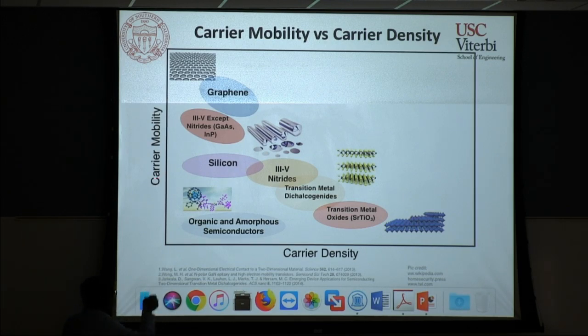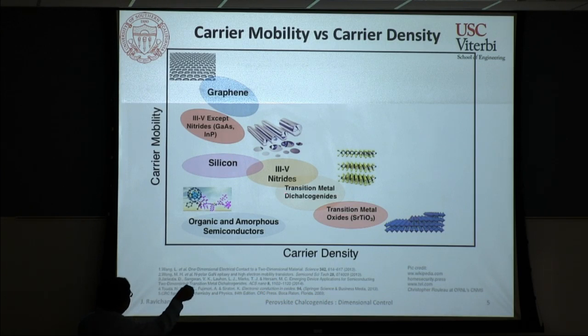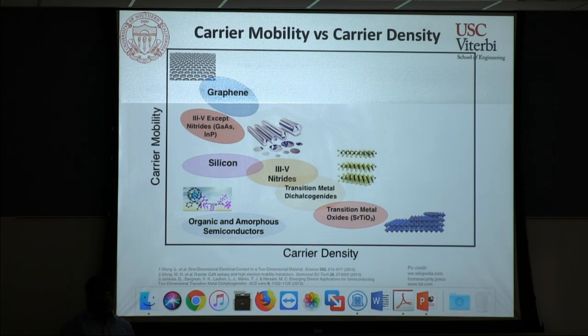These two quantities tend to go in opposing directions, so they are contradictory to each other. As you can see, some of the high mobility materials like graphene or III-V materials tend to have extremely low carrier density because the band structure itself is built in such a way that they are very highly dispersive and can only hold a small amount of charge, but they can transport extremely efficiently. But as you move down the periodic table to other materials, what you'll notice is that the carrier density can gradually increase, but that comes at the expense of carrier mobility. So we always have this issue of low carrier mobility and high carrier density, or high carrier mobility and low carrier density. So how can you get around this, and will getting somewhere here open up new opportunities? That's the big overall question that we want to ask.